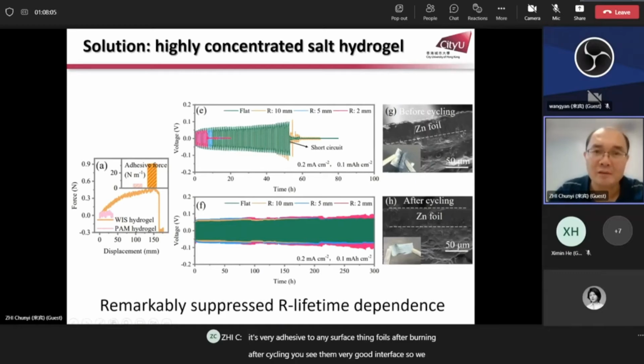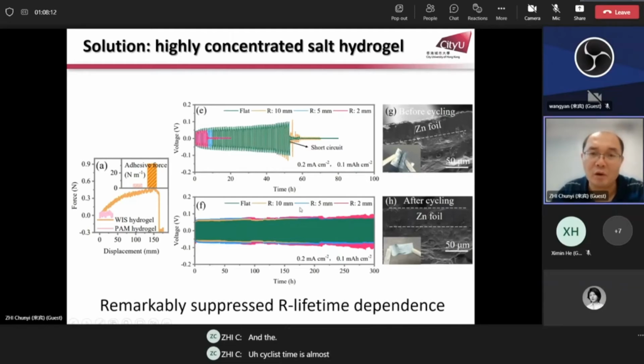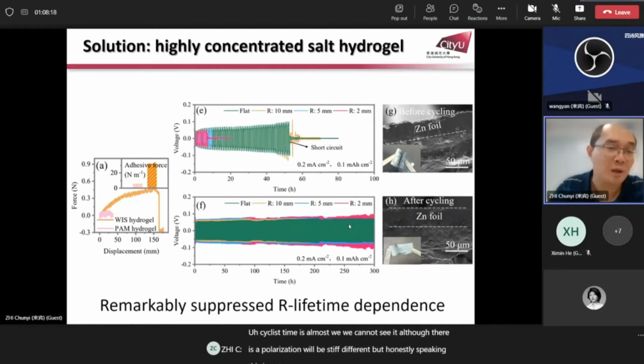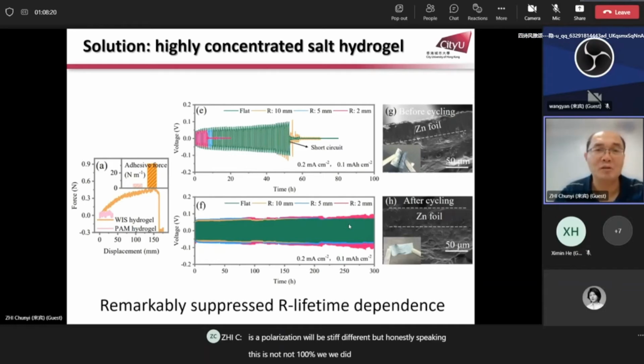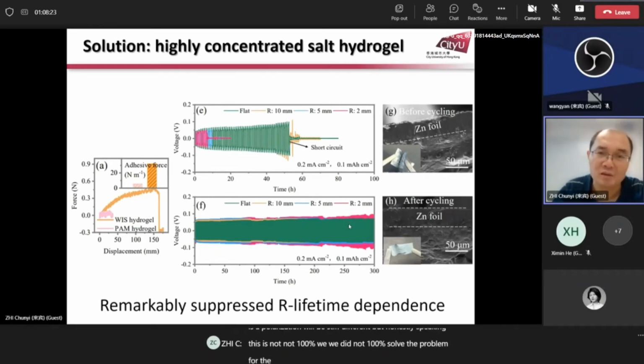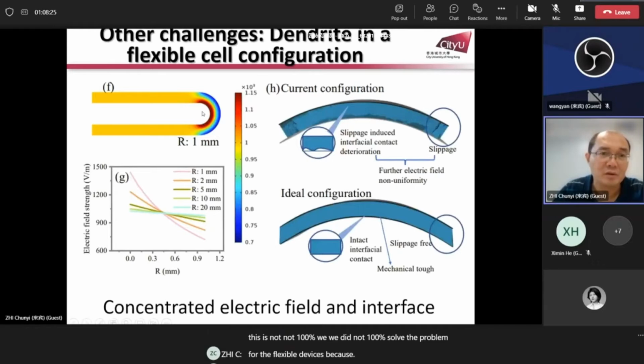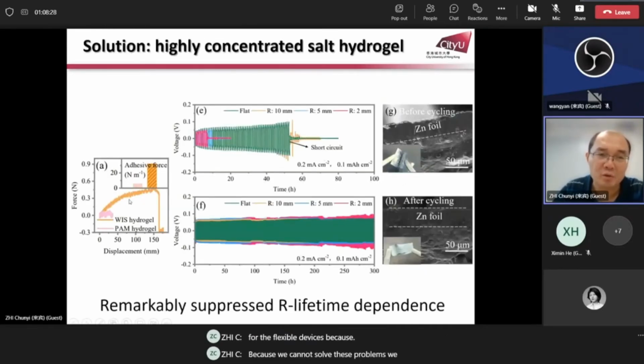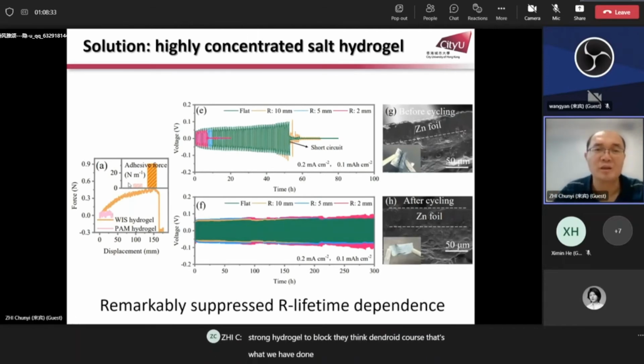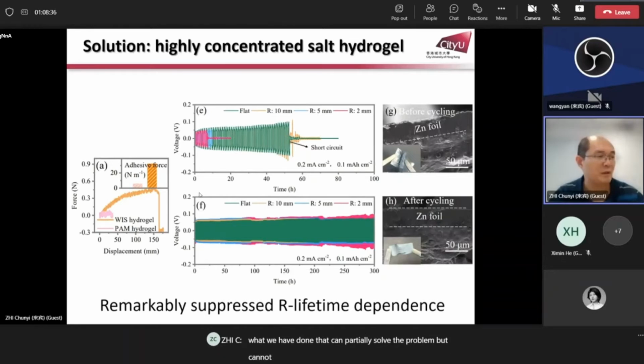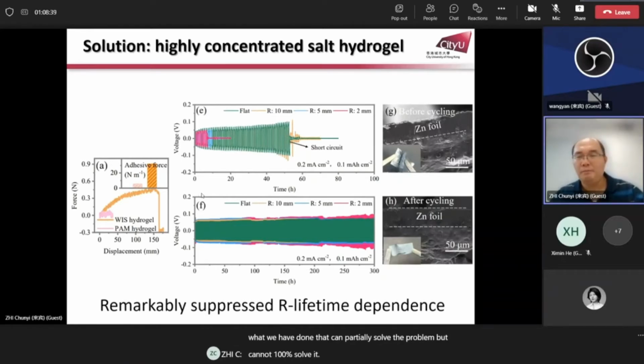So we noted that the dependence between R and the cycling time is almost gone, we cannot see it, although the polarization will be different. But honestly speaking, this is not 100%. We did not 100% solve the problem for flexible devices because we cannot solve these problems. We use a very strong hydrogel to block the zinc dendrite growth. That's what we have done. That can partially solve the problem, but cannot 100% solve it. Okay, I remember I have 2 minutes more.